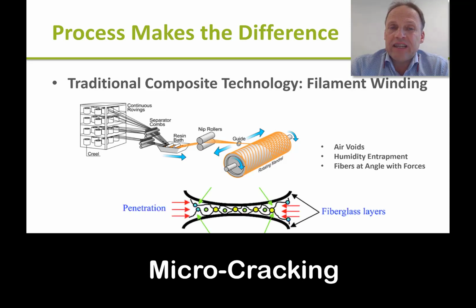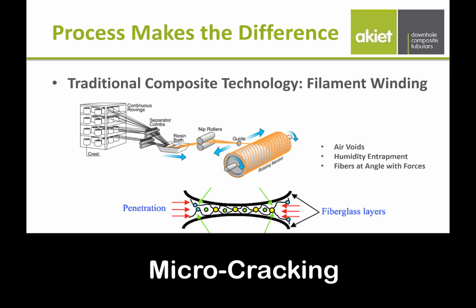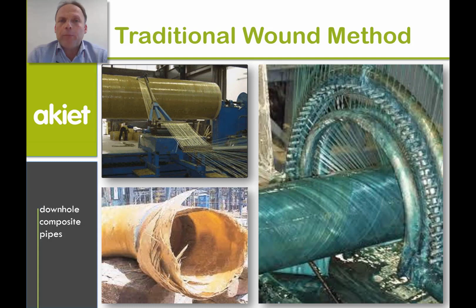And in the bottom you can see that if you have air between two different glass fibers, if there is humidity, of course you'll get propagation of fluids so much faster. You'll get pressure in those little bubbles from the pressure that's applied within the tubular, and it is going to lead to micro cracking and ultimately failure. This picture shows a typical filament winding operation. A lot of fibers at the same time being wound around the mandrel after being wetted by the epoxy.